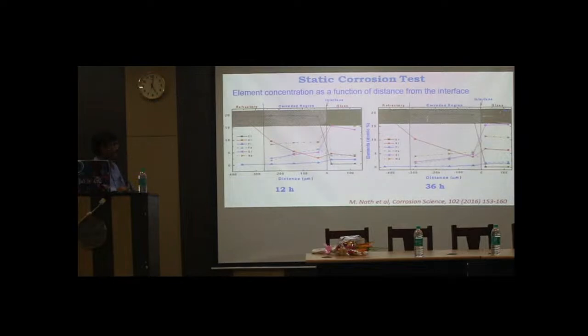And the same thing, even after 36 hours, you see that the aluminium concentration is less, but the chromium, even after 36 hours, is unchanged. So that means the chromium is not participating in the chemical reaction; only the aluminium component of the alumina chrome dissolves into, or migrates into, the glassy phase.